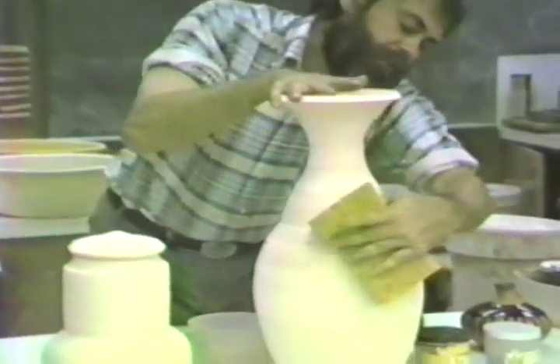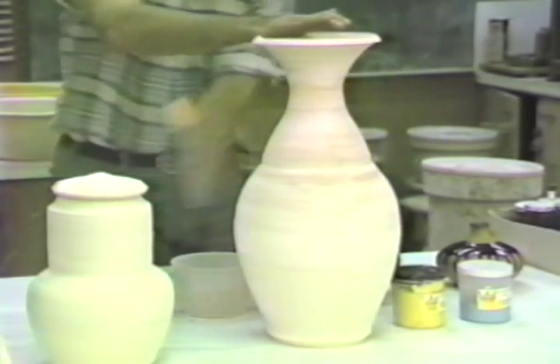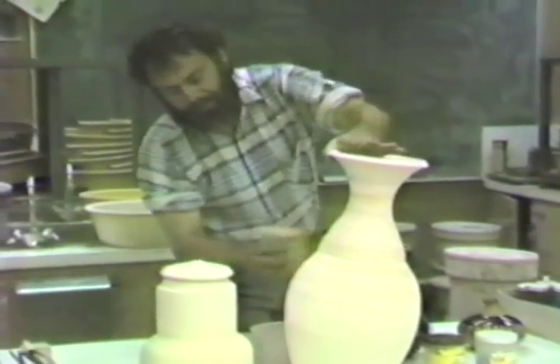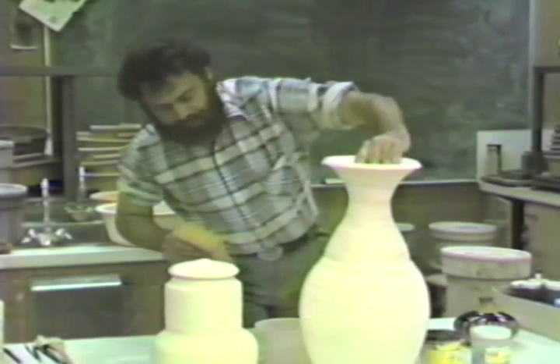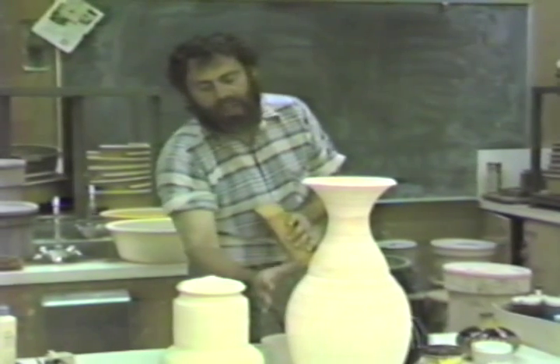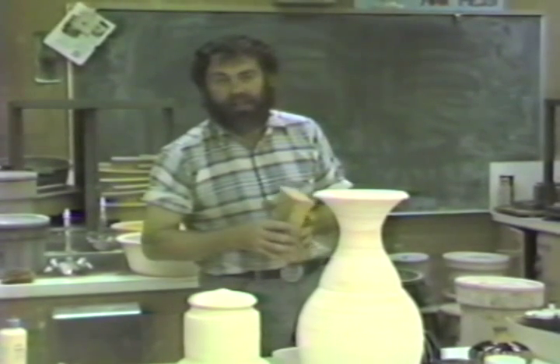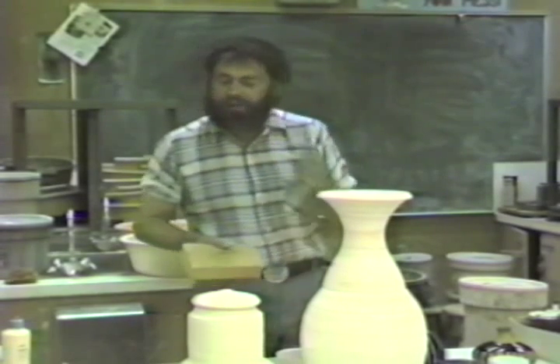And there's another reason why we want you to wipe off your pot, and that's because the glazes, if everything is the way we hope it is supposed to be, the glazes are made to a consistency that is supposed to be put on a pot that's been wiped with a wet sponge. Because the thickness of the glaze in the vat is very important. If it's too thick, then you can get too much glaze on and it can cause the glaze to crack. And if you ever have a glaze where you put the glaze on and then it looks real thick and chunky, and then as it starts drying, it'll form cracks on it like drying mud. I'm sure you've seen mud where it dries out and then kind of curls up on the edges of the cracks. That's the same effect that you would have on a pot.